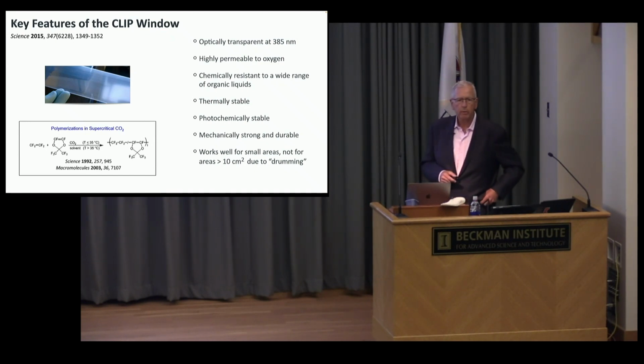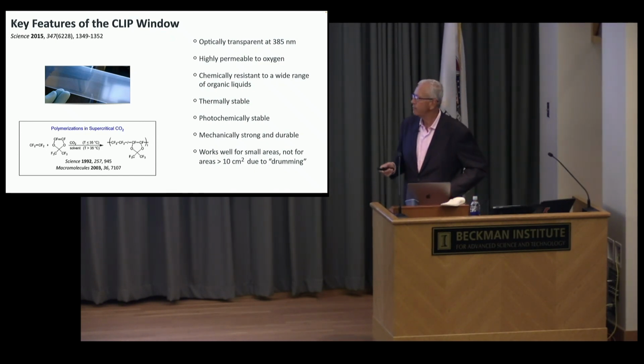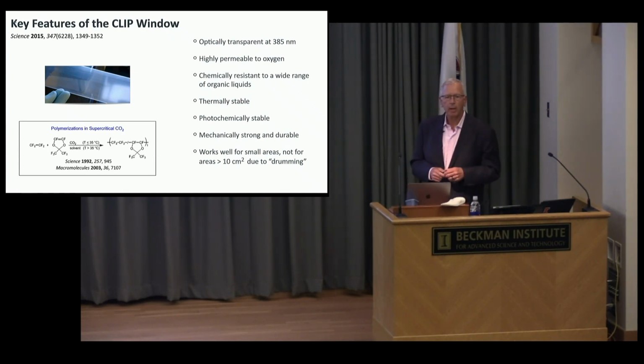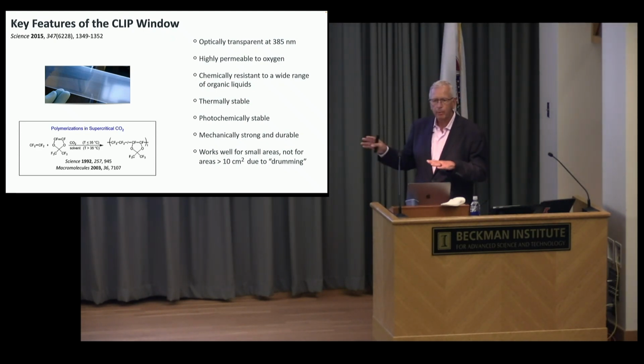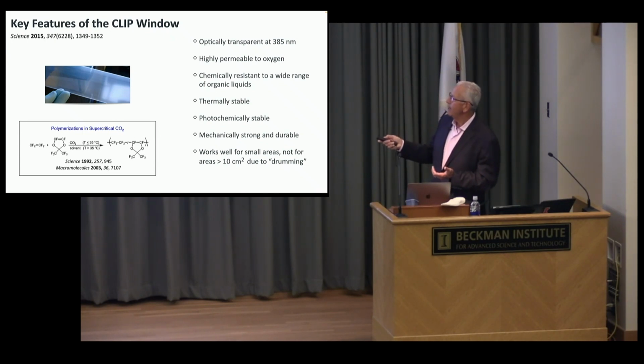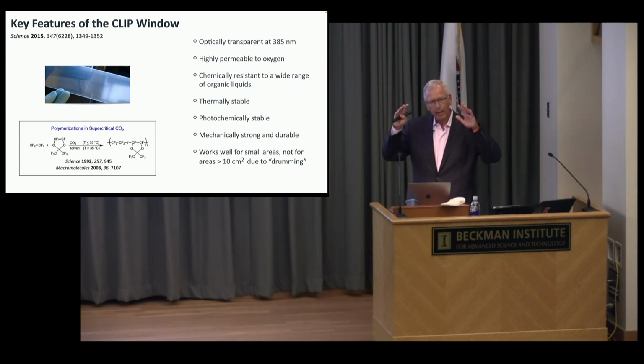And the keys to this, I'll walk through some elements of this. First, the window. The window is, in a first variation of this, an amorphous fluoropolymer, a copolymer of tetrafluoroethylene and a fluorinated dioxole monomer that breaks up the crystallinity of polytetrafluoroethylene. And so it's an amorphous glass. And this material is the most oxygen permeable material known. A lot of people are looking at it for all sorts of separation examples. But it's also not soluble in organics. It's photochemically very stable. It's an amazing material, and it's perfect for this process. And that allows oxygen to come through, and the organic doesn't dissolve into the window, as it would for silicones and other materials. And this allows this process to run.